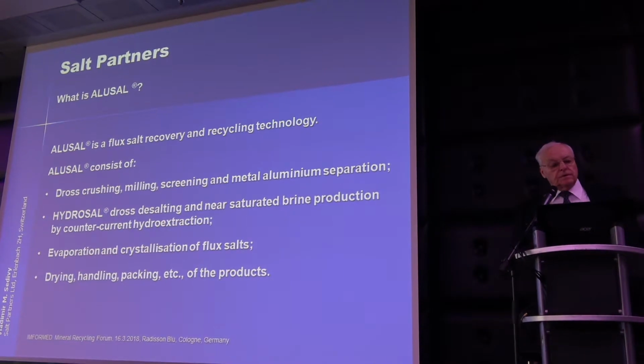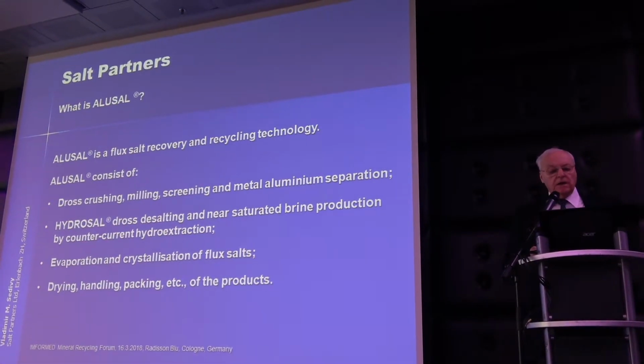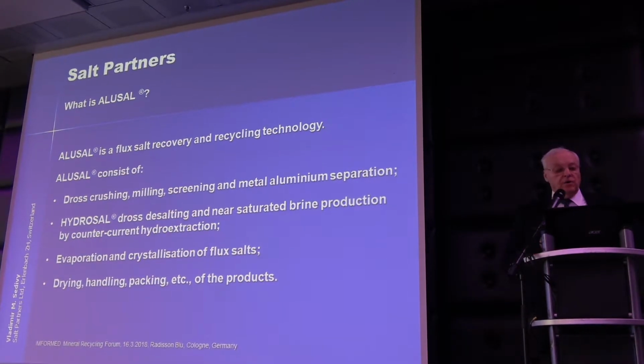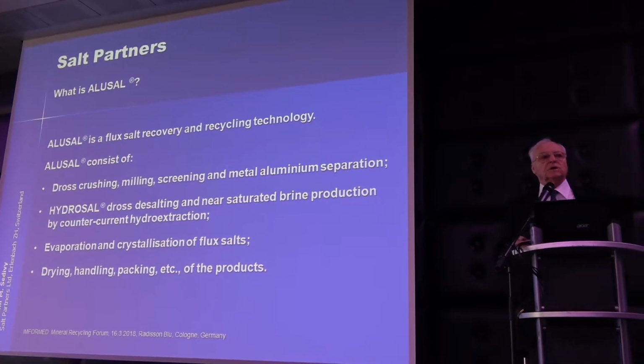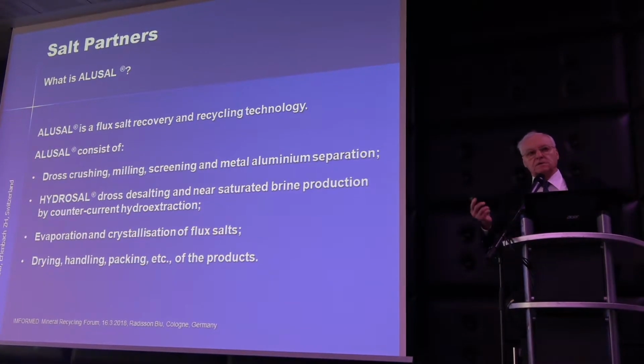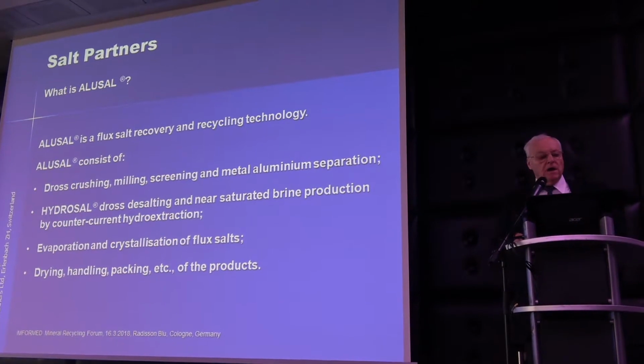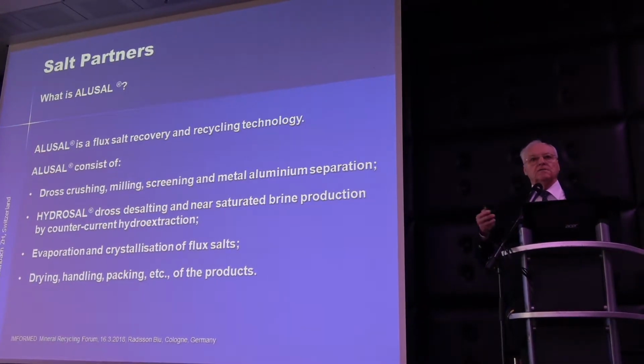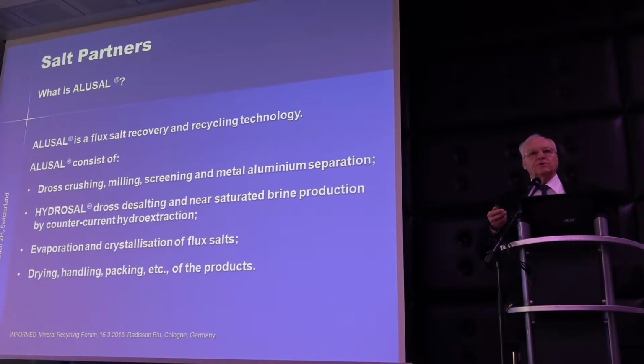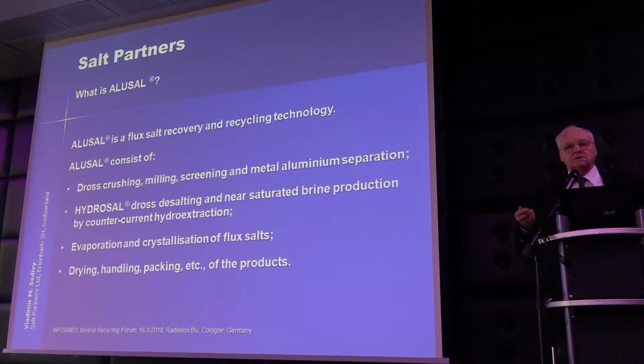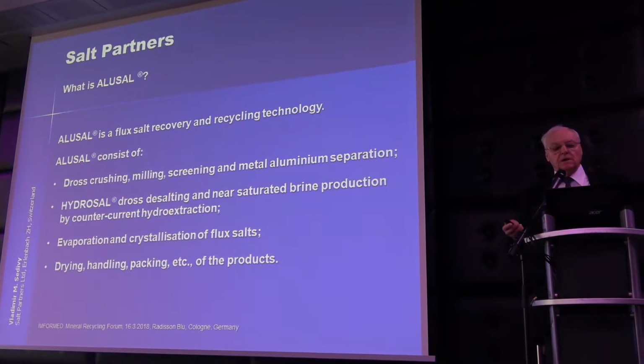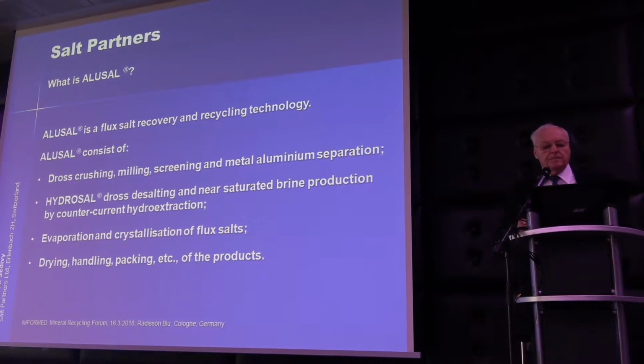First of all, the dross has to be crushed, milled, screened, and the metal aluminium has to be separated. For each one of these unit operations, you can either use something rough, as it was done here, or something more sophisticated. For example, the crushing and the milling can be done in phases, and then you are producing much less of the very fine dust that is unpleasant. Also, the metal aluminium can be separated just by screening, or even by some eddy current separators. The Hydrosal process is the key of this process.